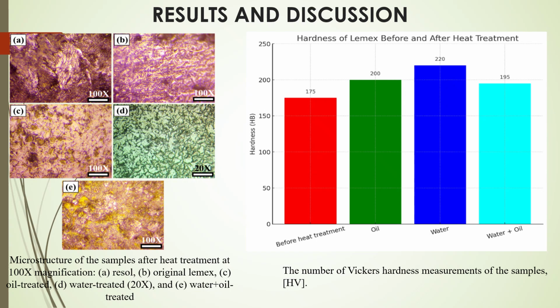On the right, we have the hardness test results. Before heat treatment, the Lemex hardness was around 175 HB. After oil quenching, hardness increased to 200 HB. With water quenching, it further improved to 220 HB, which is the highest value recorded. For the combined water oil treatment, hardness was slightly lower at 195 HB. From these results, we can conclude that heat treatment significantly enhances hardness of Lemex, with water quenching showing the best performance. These improvements mean that the plowshare will have better wear resistance, longer service life, and higher reliability when used in agricultural conditions.